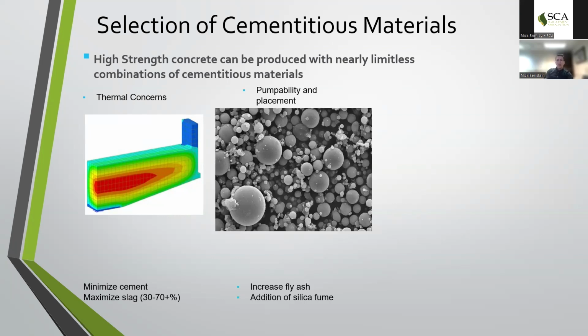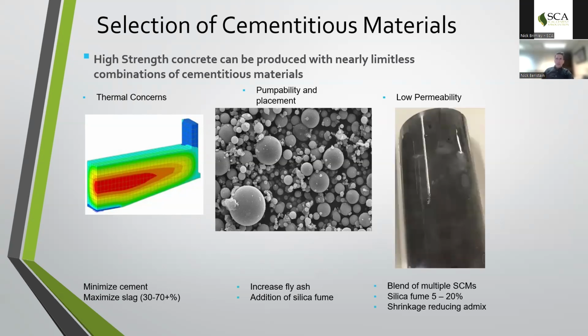In terms of other placement concerns and pumpability, managing things through self-consolidating concrete, particularly with high pumping or rebar congestion, can really help with the addition of slag cement to provide stability to the paste matrix. Along with that, the use of fly ash and potentially even silica fume can also help. And finally, achieving long durability, low permeability concrete is usually a blend of all of these materials. Slag cement continues to be the majority of the SCM we consume in designing high performance concrete, but pairing that with a blend of fly ash usage and even a low dose of silica fume can develop an incredibly robust and low permeability concrete that can help eliminate concerns with cracking, shrinkage, and overall penetration into the element itself through the concrete matrix.